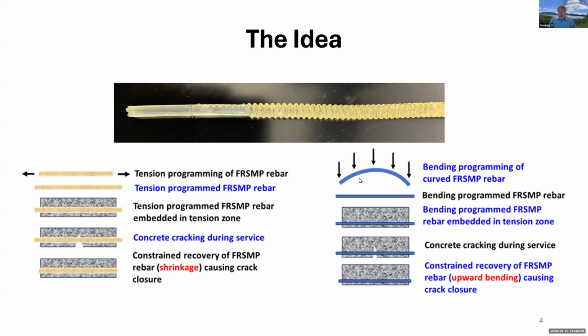Of course, you can also prepare a smart rebar, let's say with a curved shape, and then you can do a compression programming. It becomes a straight bar, and then you embed it into the concrete beams. So later, the straight rebar will try to bend back if you apply a negative moment to the concrete beams. In such a way, you can also either narrow or fully close the crack. So this is the idea.